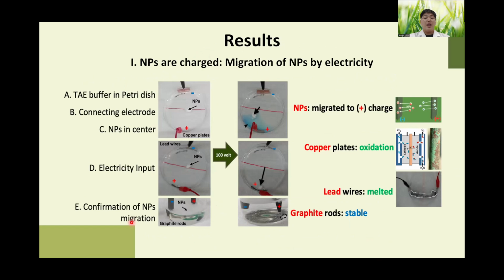As a result of checking the electrical mobility of the nanoplastics by using copper plates, lead wires, or graphite rods, I confirmed the nanoplastics migrating toward the positive electrodes. It is noteworthy that the copper plates and lead wires were severely destroyed, whereas the graphite rod remained stable. It means that graphite can be reused for optimal electrodes.